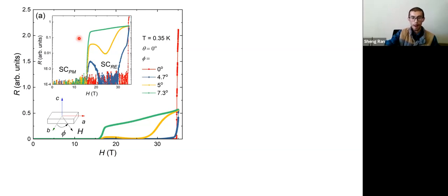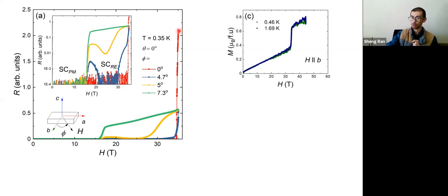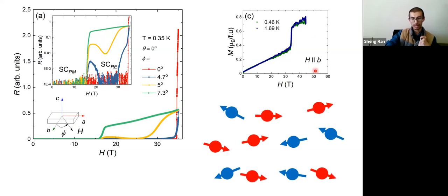All right, so I showed you this data. I'm showing you again. You have 0 resistance up to 35. It goes to a normal state. But we want to ask, what kind of normal state this is? With the magnetization study, here we can see in the magnetization along the b-axis, it linearly increases, and there is a sudden jump in the magnetization, indicating likely the magnetic moment was along a different axis.